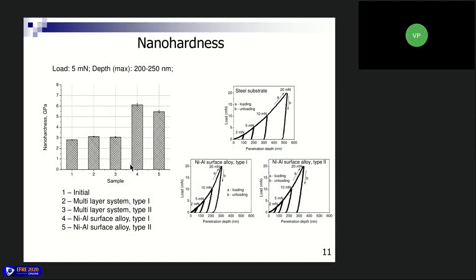And for the nanohardness, the same 5 samples, and also the initial sample and the multilayer systems have quite the same results of nanohardness, about 3 gigapascals. But for the surface alloys, the nanohardness is significantly higher, up to 2 times, to 6 gigapascals for surface alloy type number one.